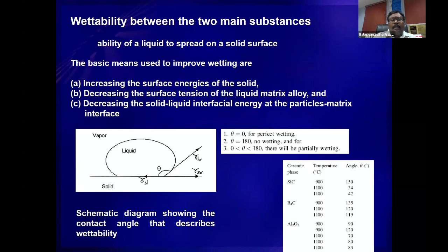Then another important thing is the wettability between the main substances. It is the ability of a liquid to spread on a solid surface. So one can increase the wettability by increasing the surface energy of the solid, that means the reinforcement, and decreasing the surface tension of the liquid, that means the matrix metal. Decreasing the surface tension of the liquid matrix metal is possible by increasing the temperature, so the viscosity will come down. And increasing the surface energy of the solid is done by preheating the solid. This combination decreases the solid-liquid interfacial energy at the particle-matrix interface.